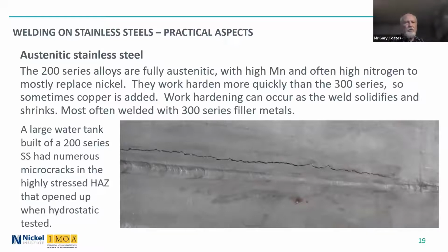And I'll just show an example of a large water tank. It was built using a 200 series stainless steel, I think about 15 millimeter thick plate. There were numerous micro cracks in the structure, which were not obvious to the welders. And when they filled the tank full of water, there were quite a number of cracks that looked like this that needed to be re-welded again. So there can be some issues with thicker 200 series, not so much on the thinner materials.